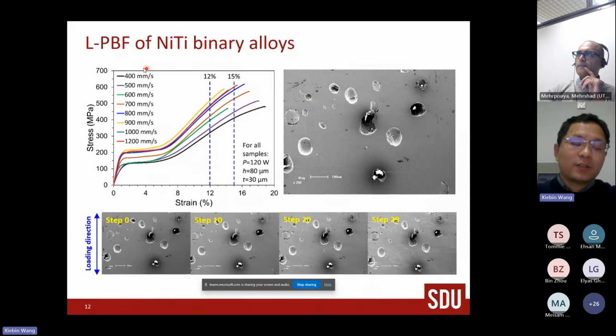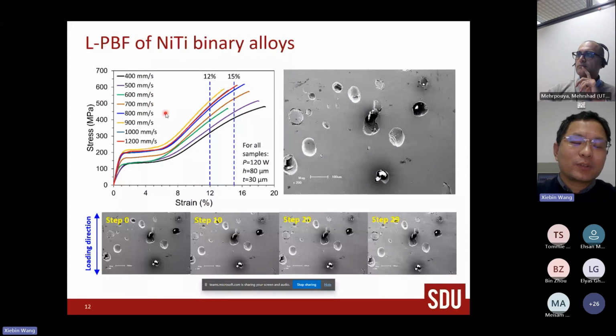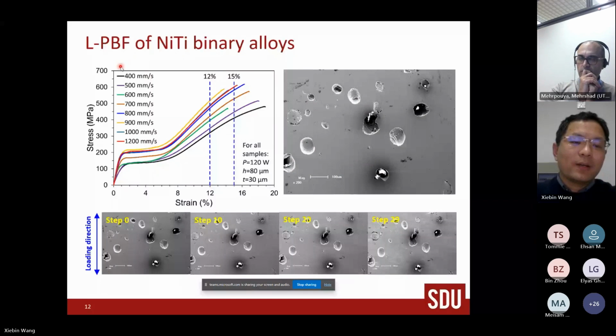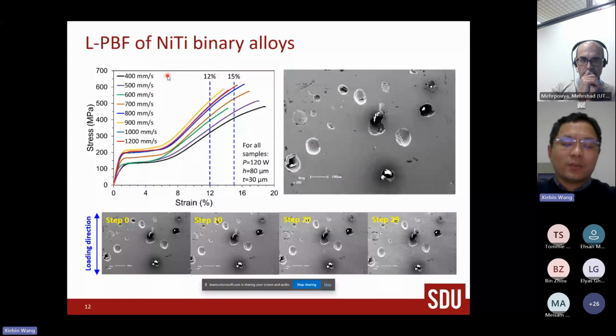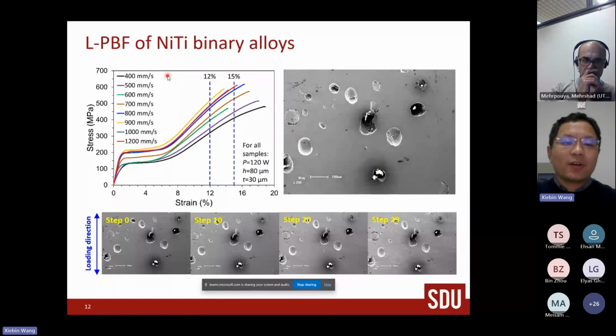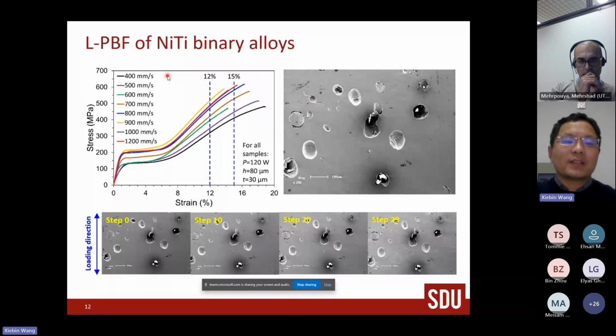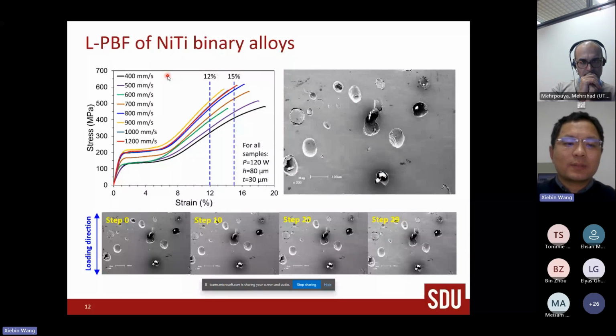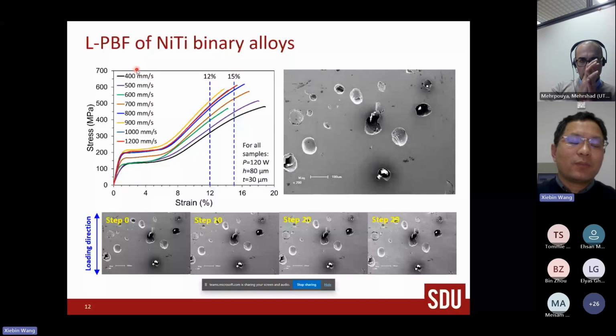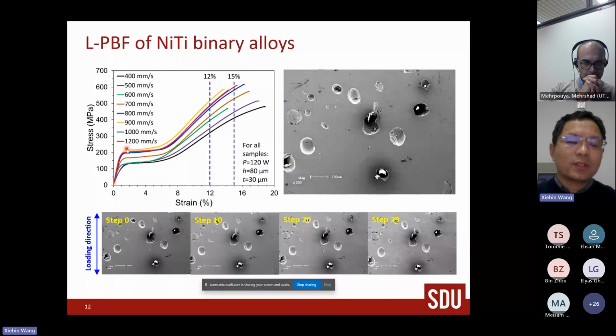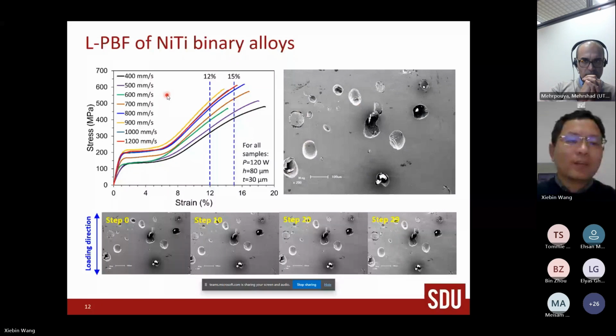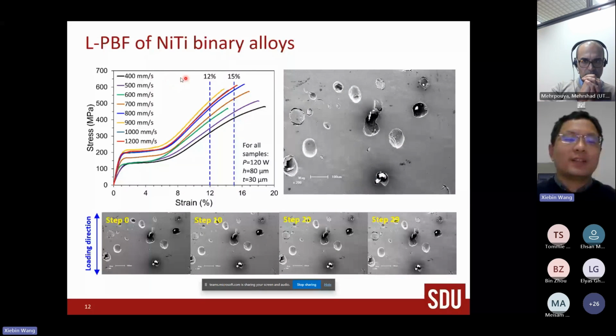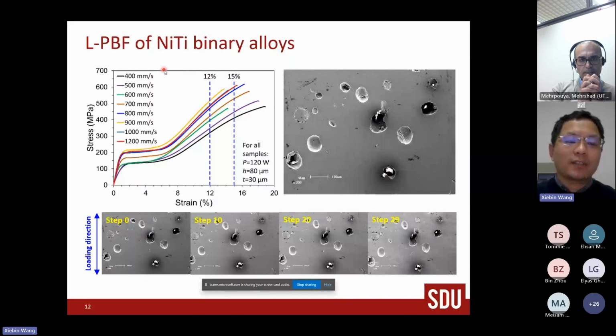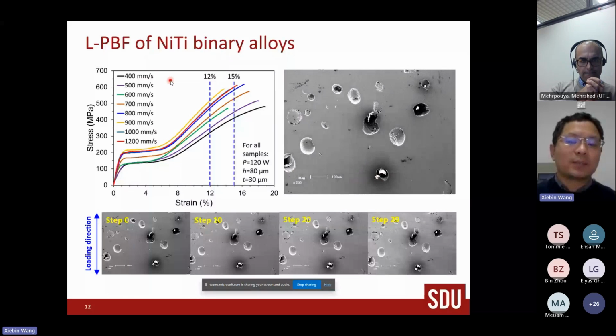And if you want to tailor transformation temperature, you have to modify the process parameters. But if we learn from the LPBF of other alloys, normally you need optimized process parameters to get a fully dense material. But here we change the scanning speed from 400 millimeter per second to 1,200 millimeter per second. Of course, this will cause a lot of defects in this material with a high energy input, like the 400 millimeter per second sample.